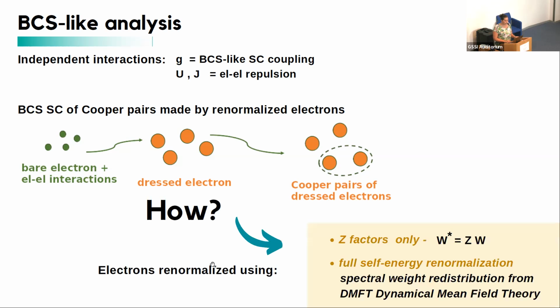And the way I can renormalize the electron, of course, I can use different approximations. What I'm going to do is compute with dynamical mean field theory the full frequency-dependent self-energy renormalization. I made the calculation with this, but I also want to check the effect of the quasi-particle coherence exactly at the Fermi level. So I'm going to extract at low frequency the renormalization factor for the kinetic energy Z, and I'll show you results also for this approximation.